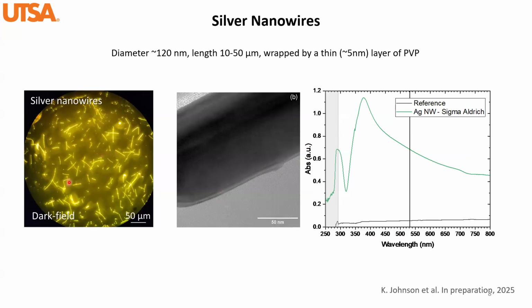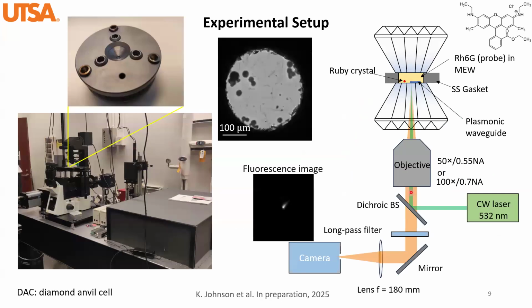On the left side is a dark field image of the silver nanowire. Here's a TEM image, and there is a spacer here, the PVP spacer. On the right side is UV-vis spectroscopy of the silver nanowires, which has a typical peak around 370 to 380 nanometers. And this line at 532 marks our excitation wavelength in our experiment.